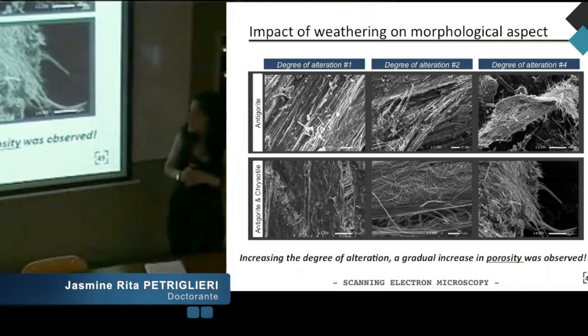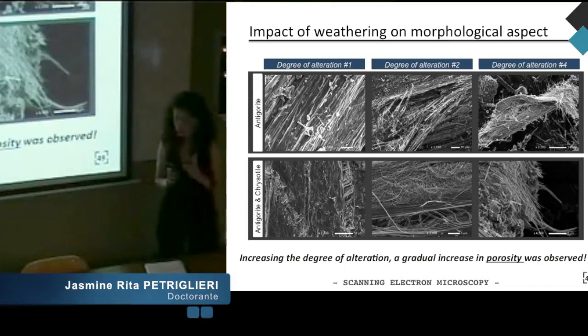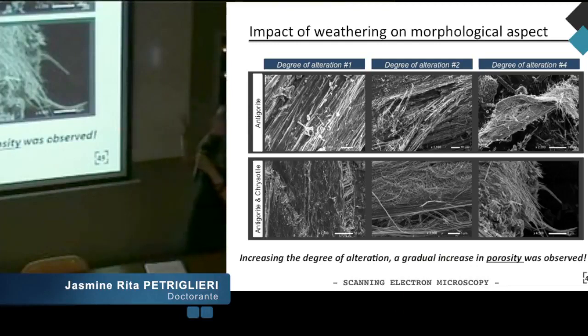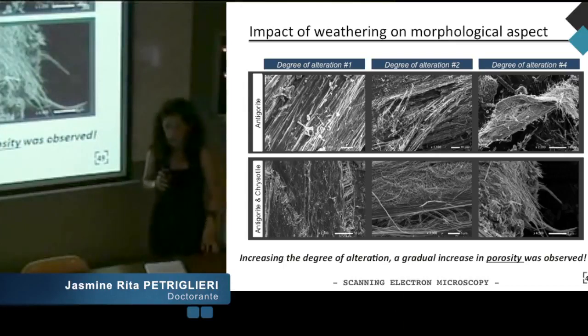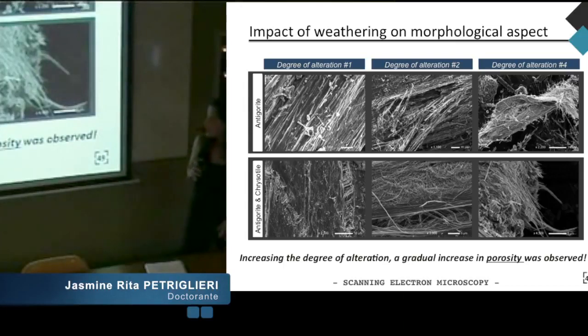Evaluating the weathering on morphological aspects for antigorite and mixed phase antigorite and chrysotile, we observed that increasing the degree of alteration from 1 to 4, for antigorite especially, a gradual increase in porosity was observed. The space between the fibrolamellae correlated with the increase of state of alteration. In the case of antigorite and chrysotile samples, this factor was more important because probably the penetration and circulation of fluids and water between fibrils and lamellae is facilitated in the fibers of chrysotile, opening the structure and generating the formation and release of fibers into the environment.